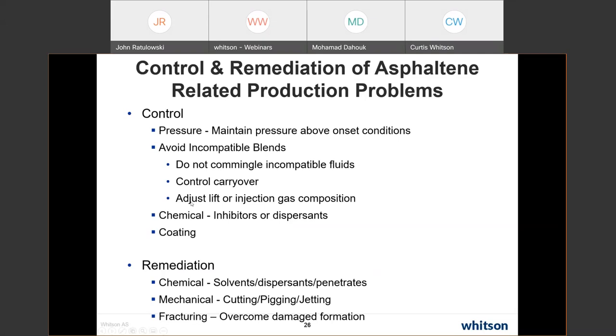You may want to adjust your lift gas composition if possible. If you dry these up, so they're primarily methane, they'll have less tendency to cause issues with asphaltene destabilization.